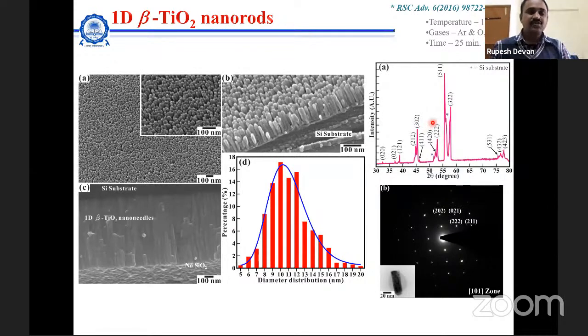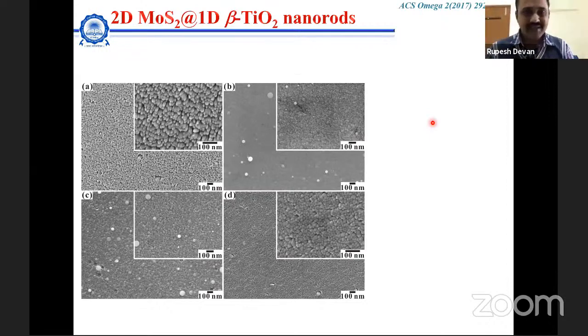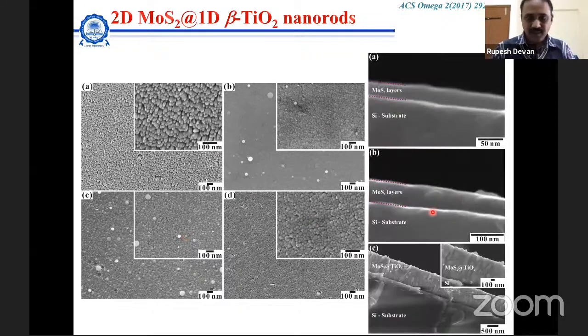After that, the challenge was how to put this MoS2. So we decided to go with a thin layer of 4 nanometer of MoS2 over TiO2 so that these one-dimensional structures remain intact. Then we slowly increased the thickness of the MoS2 over it, reaching 20 and 40 nanometer. Then we confirmed how much layer was forming. We can see here in the cross-sectional view that MoS2 is covering the TiO2, so this became quite compact.